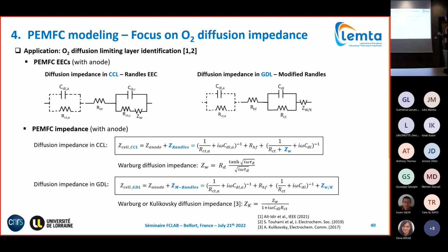And in this case, we tested as well an alternative to the Warburg diffusion impedance, which was developed by Andrei Kulikovsky, which took into account the impact of the reaction kinetics at the cathode on the oxygen diffusion through the GDL. Physically, this is our circuit on the cathode side here, with the high frequency resistance again representing the membrane. And just note here the dotted lines are the representation of the anode this time, because we needed this for our spectra analysis.